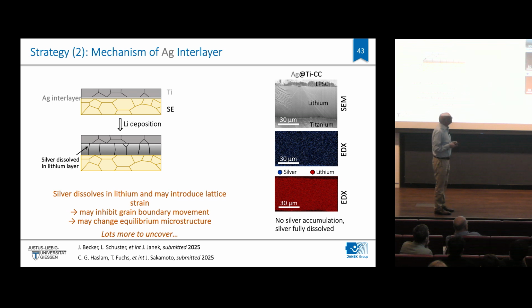Now, the second thing is if you go for silver: silver is completely dissolving in lithium. The phase diagram is that way. Silver completely dissolves. It seems that also the dissolved silver, you have a silver interlayer, you grow your lithium film, the silver dissolves in the film and changes also the mechanical properties and the diffusion behavior of the lithium. If you strip it again, you reform the silver film, so it works reversibly and then influences your lithium growth. It's, I would say, metallurgy in the battery. And this is something that has been really overlooked, which role metallurgy will play in a battery. Chemists are not well trained, I would say, in metallurgy.